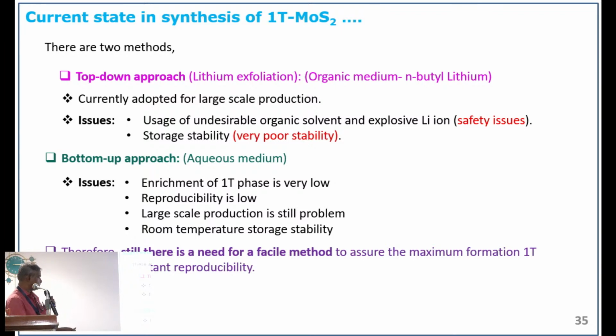So there is still a need for a facile method to achieve the maximum formation of the 1T phase with constant reproducibility. The very important thing is you have to produce the 1T phase in 90% or 95%, but similarly the reproducible results should be there. If you use the same volume or same amount of precursors, you have to end up with the same amount of 1T phase and the same quantity of material. So that's very important in this case.